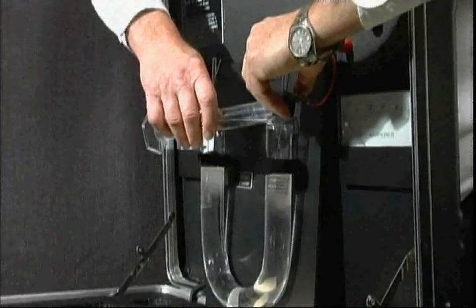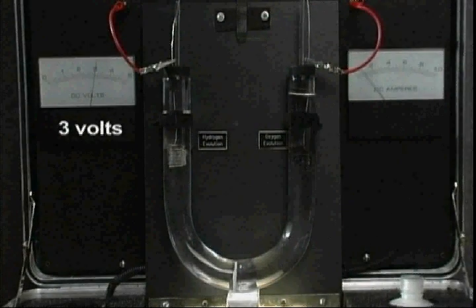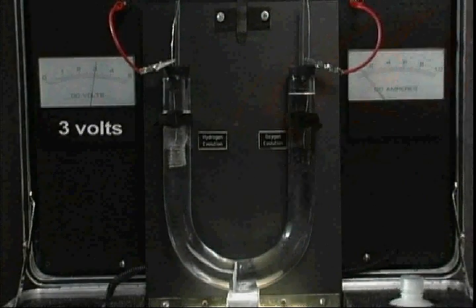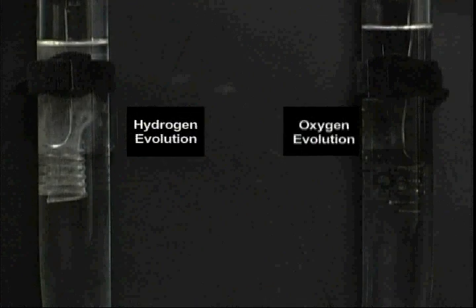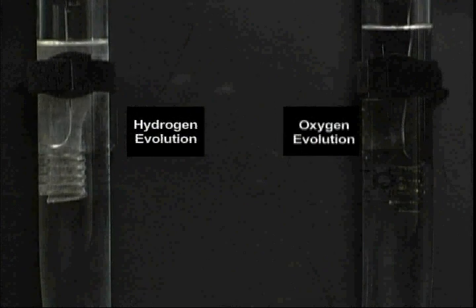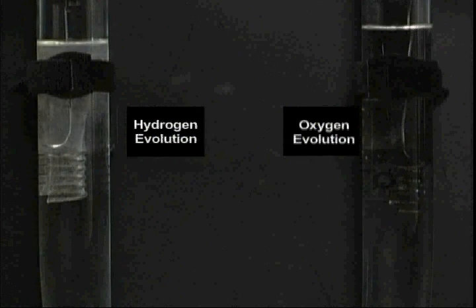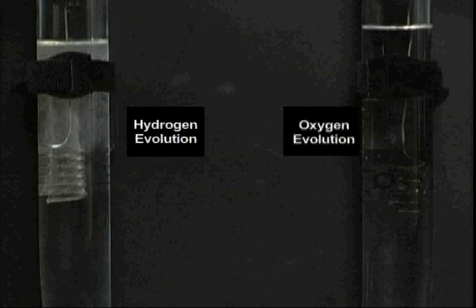This will cause the reaction to change. It is much more favorable to consume methanol than to evolve oxygen. At 3 volts, we again see vigorous evolution, but now only at the hydrogen electrode. There is no gas evolution at the oxygen electrode. This is direct evidence that the mechanism at this electrode has changed.